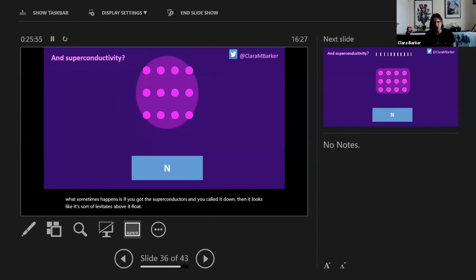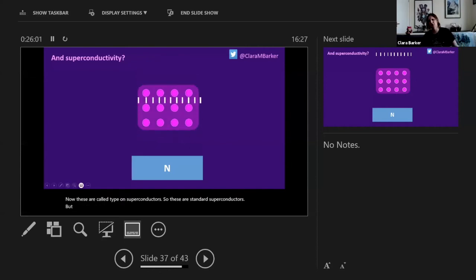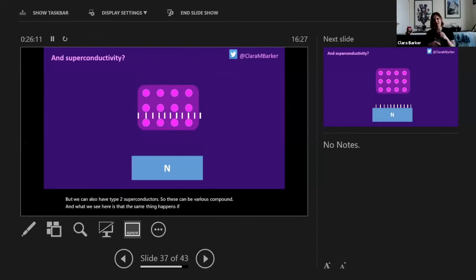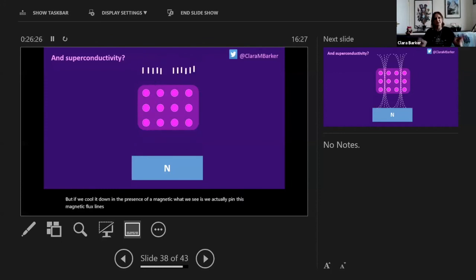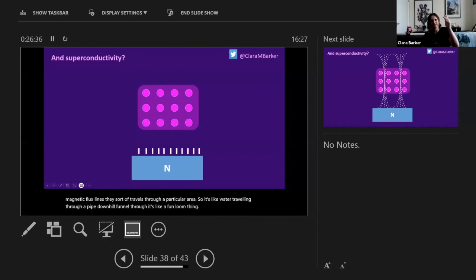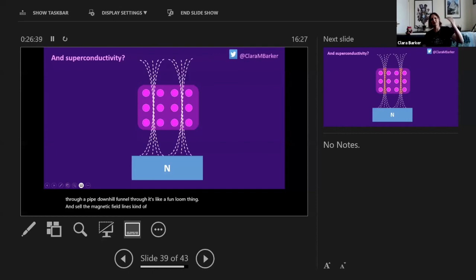Now these are called type 1 superconductors, so these are our standard superconductors. But we can also have type 2 superconductors, so these can be sort of various compounds. And what we see here is that the same thing happens. If we cool a superconductor down without the presence of a magnet, the magnetic field lines are expelled. They'll no longer travel through, they have to travel around the material. But if we cool it down in the presence of a magnet, what we see is we actually pin these magnetic flux lines. They sort of travel through a particular area. So it's like water traveling through a pipe downhill. It'll funnel through. It's like a funneling thing. And so the magnetic field lines kind of want to stay where they are. They want to travel in that same direction.